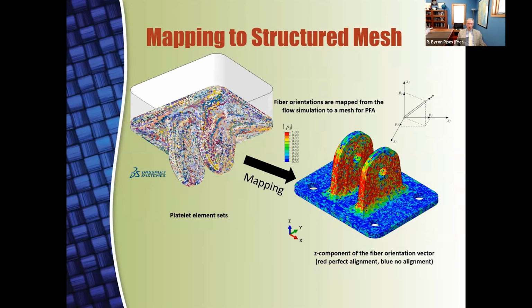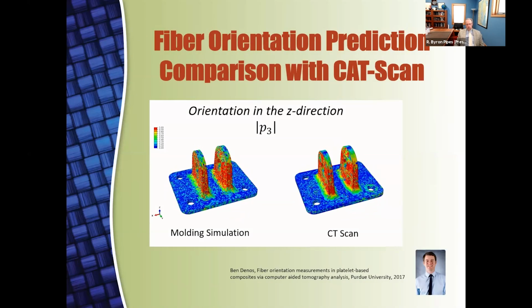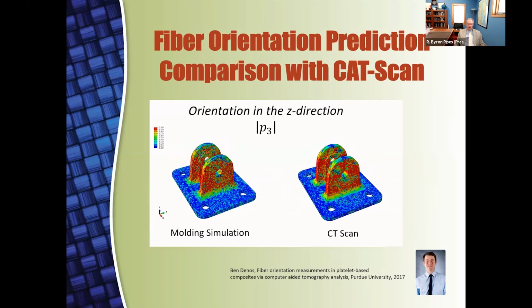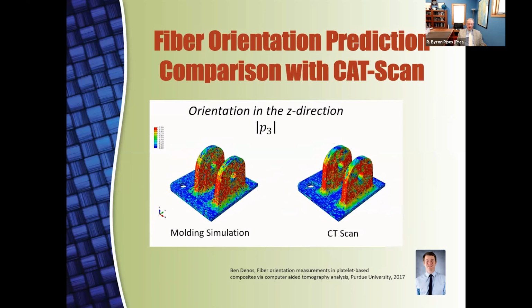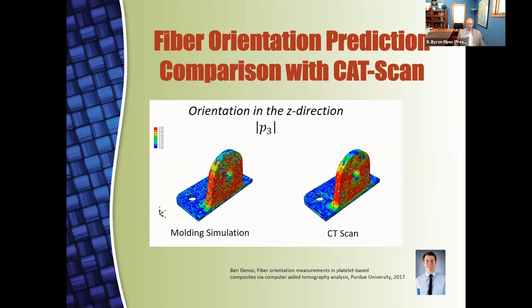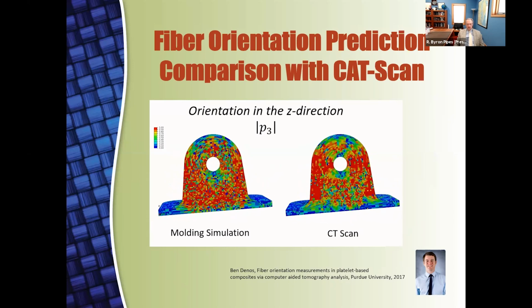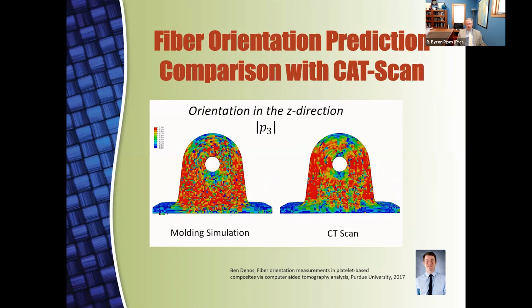The question is, how well are these predictions working? And to do that, the next student worked on computer aided tomography analysis, and what you see here is a molding simulation on the left and a CAT scan on the right. It's not a simple process to do a CAT scan and still preserve the large scale dimensions in the system. And Ben was able to do that with a very interesting density gradient methodology that he applied in his doctoral dissertation of 2017. I think you would agree that the molding simulation and the CAT scan results show very good comparison.